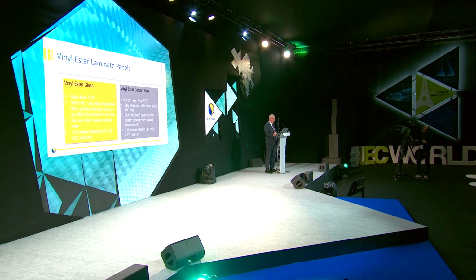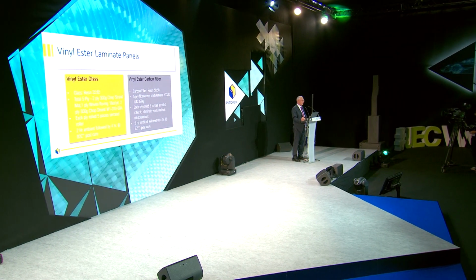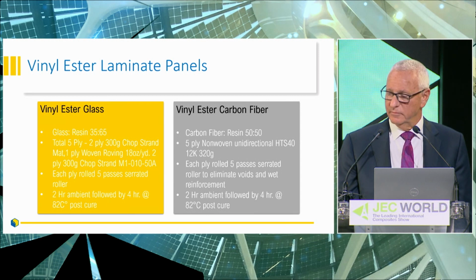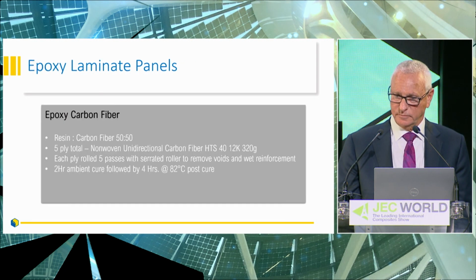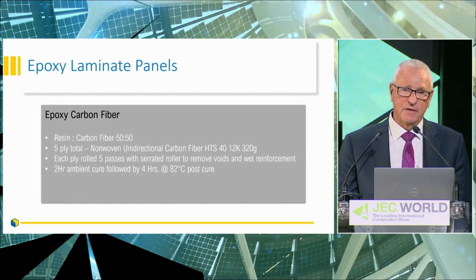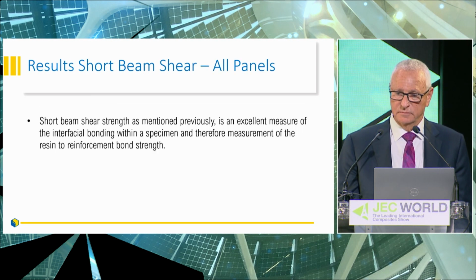Again, we can go through these fairly quickly. We did the carbon fiber resin at 50/50, glass to resin. The vinyl ester glass we did at typical 35/65. They were 5-ply laminates. The glass had chop strand 450, 4 plies with 1 ply woven in the middle, and I just picked a carbon fiber, a non-woven unidirectional, for the carbon fiber. And then the epoxy carbon fiber, again, a 50-50 5-ply. They were all rolled out equally as you can do it in a hand-laid laminate. Everything was 2-hour ambient, followed by 82-degree oven for 4 hours. So as I said, short beam shear is an excellent measure of interfacial bonding.